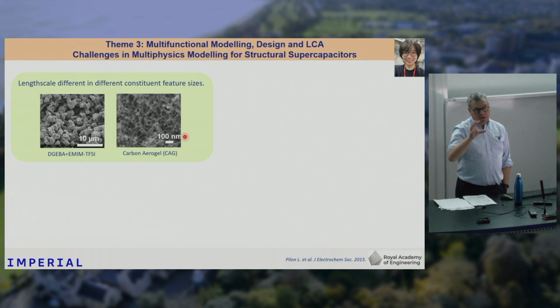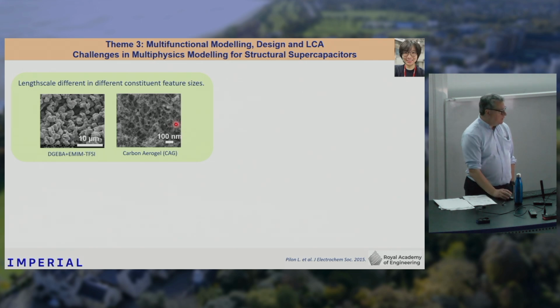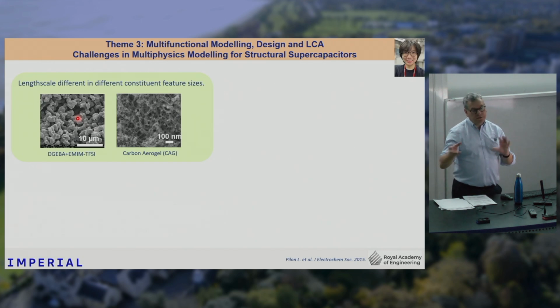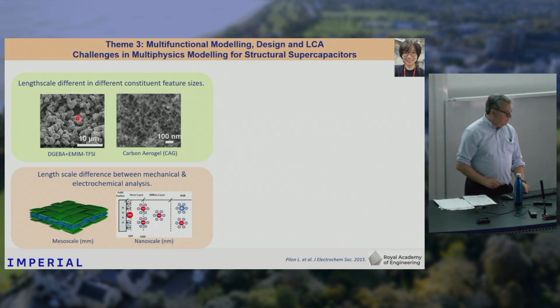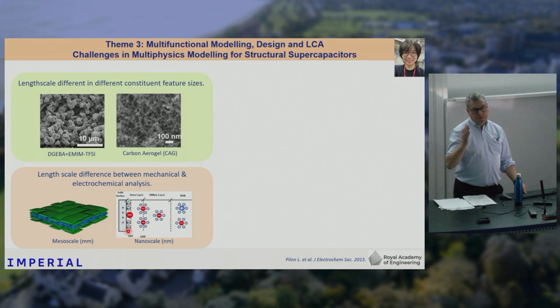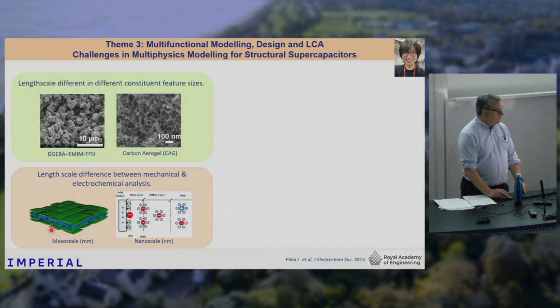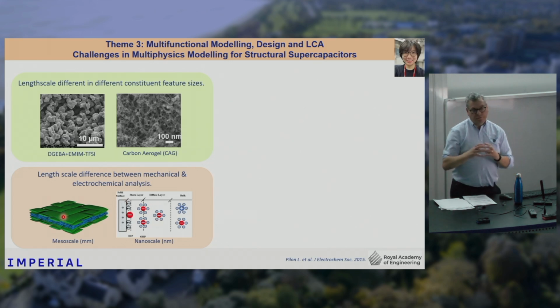So you've got a really fine microstructure in your electrode, but in your electrolyte, it's the order of microns. So immediately you've got 3 decades difference in terms of the length scales that are there. We have a difference in the length scale in the actual physics that's going on as well. So as I mentioned before, most of the charge is stored at this double layer between the electrode and the electrolyte, which is the order of a nanometer in scale. But then if you're looking at mechanical modeling of the material, it's a mesoscale problem.